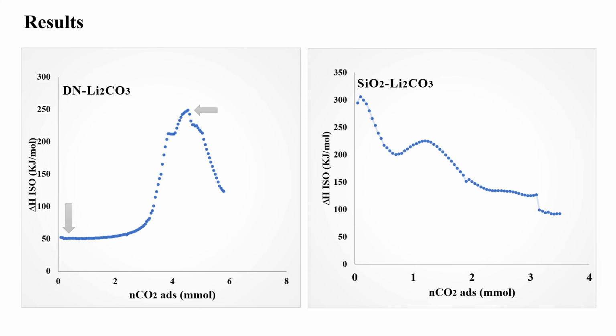Secondly, for the second lithium silicate based on pure silica, the isosteric energy decreases from 300 kJ per mole as soon as the saturation, without coming out of the chemisorption, even at high adsorption content. These results, and especially for the lithium silicate sorbent based on diatomite, offer a great advantage for the adsorbent regeneration because of the low adsorption energy.